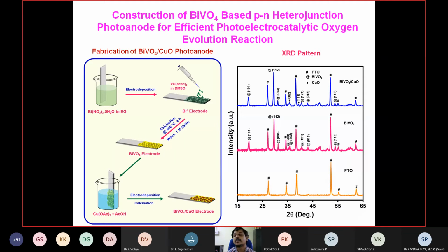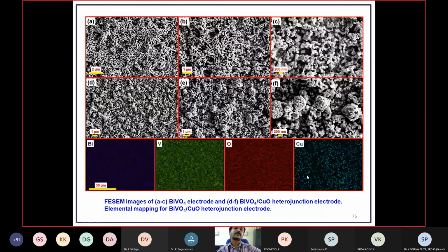So the XRD pattern clearly reveals the formation of bismuth vanadate, and in this bismuth vanadate copper oxide heterojunction, you can see some additional peaks. That is due to the copper oxide. Also, the reference pattern for the FTO is given here because we have fabricated this material over the FTO.